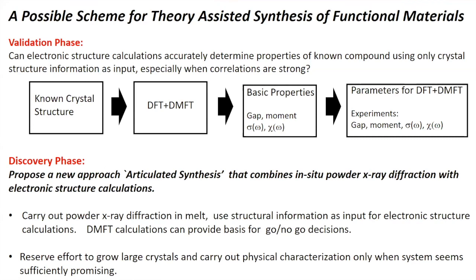And the idea then would be that if the calculations are more straightforward than actually growing the materials themselves, that is, that they would take less time, then this would be a viable route for making decisions about which materials you'd like to focus on, even without making those materials at all. And this would allow us then to reserve the considerable effort that's required to grow large crystals for the most promising compounds and really dig in to carry out the physical characterization, but only when the system seems sufficiently promising. So that would be the scheme.